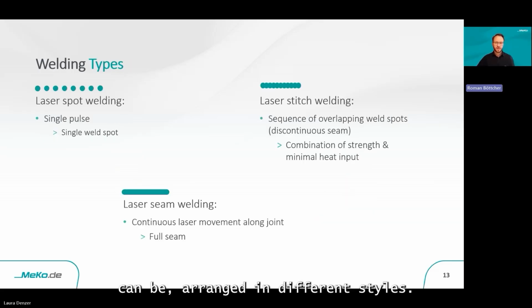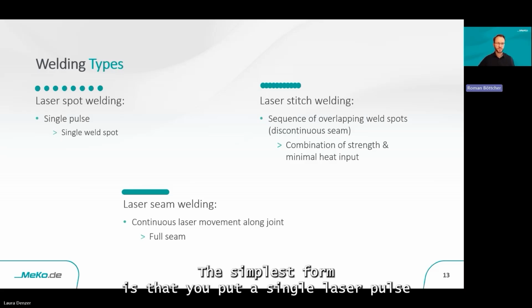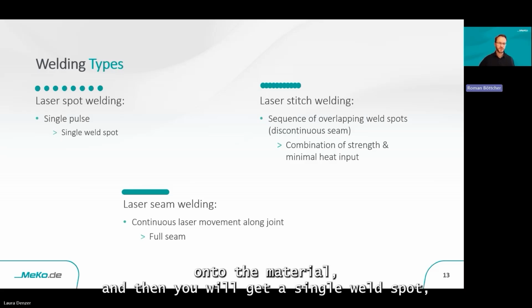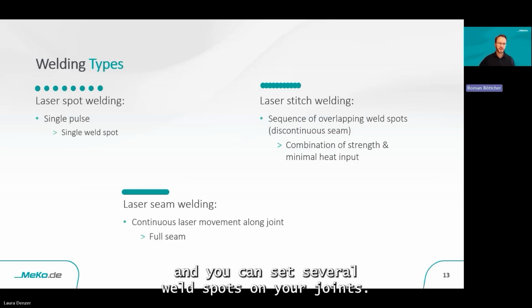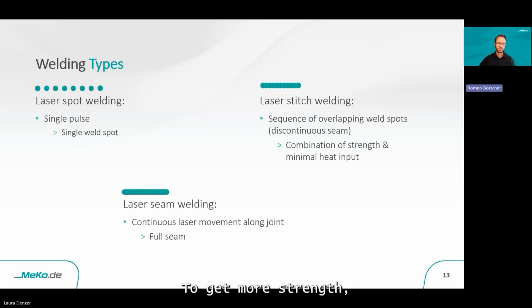The welds can be arranged in different styles. Let's start on the upper left side. The simplest form is that you put a single laser pulse onto the material, and then you will get a single weld spot. And you can set several weld spots on your joint to get more strength. You can even overlap your single weld spots. Then you will get a laser stitch welding. It looks like a seam, but it's not continuous, it's discontinuous.